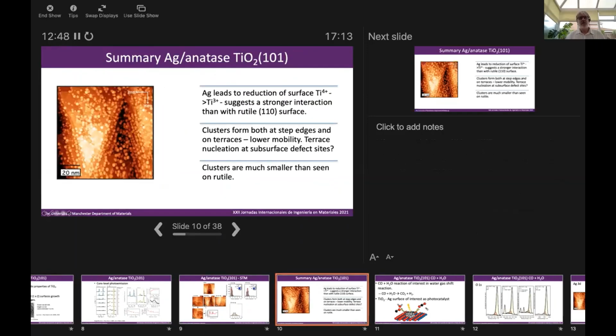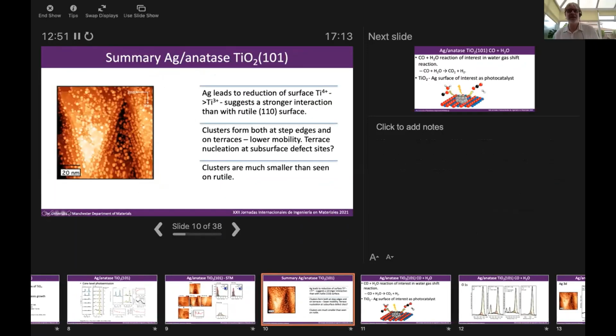And so what this really told us was that the silver leads to reduction of surface titanium 4+, which suggests a stronger interaction between silver and anatase titanium dioxide than with the rutile 110 surface. There appears to be some charge transfer from the silver into the rutile, sorry, into the anatase 101 surface, which doesn't occur on rutile. The clusters form both at step edges and on terraces, so that suggests that silver atoms have a lower mobility on the anatase surface.